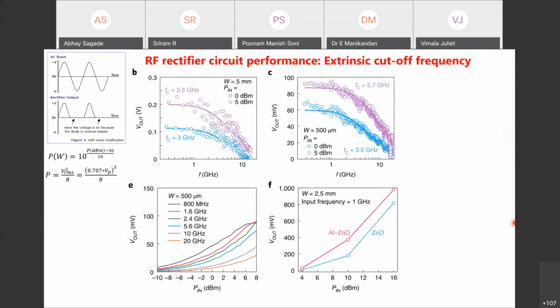So I will start with the extrinsic performance of the device. This is the DC output voltage, which is plotted as a function of frequency, for a diode which has dimensions of 5 mm and 500 micrometer. This data was obtained for two input powers, 0 dBm and 5 dBm. As you can see, for 0 dBm, the cutoff frequency shown here is 3 gigahertz, and when you increase it to 5 dBm, it goes to 3.6 gigahertz. For the larger device. When you make the device dimension smaller, you can see this cutoff frequency is increased from 3.6 to 5.7 gigahertz.